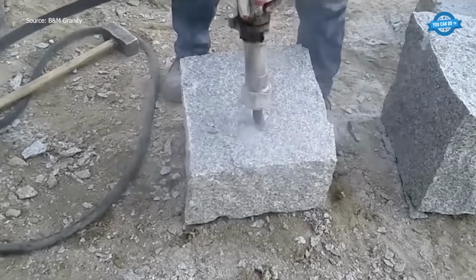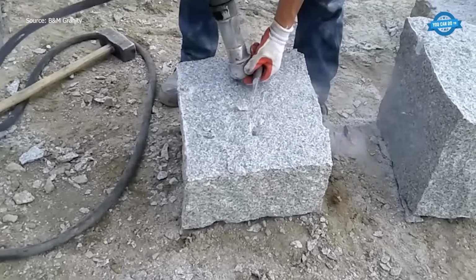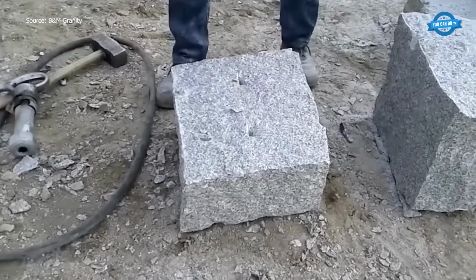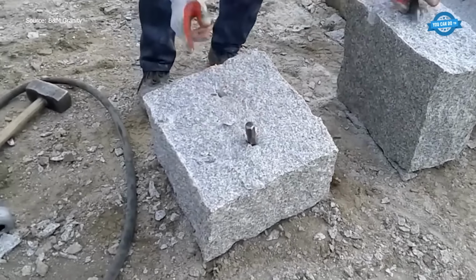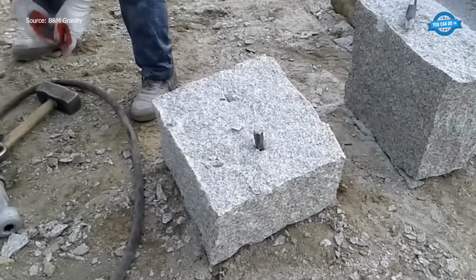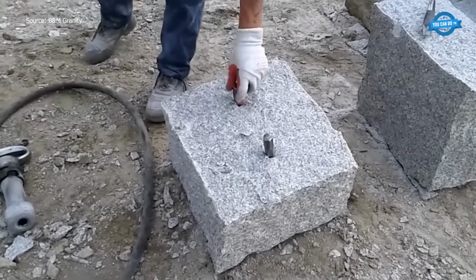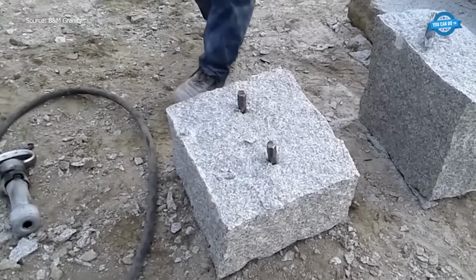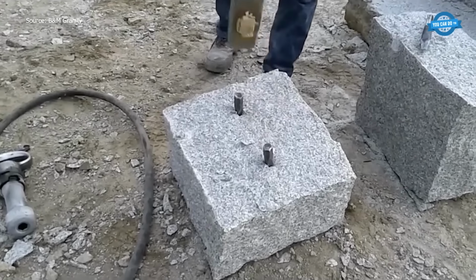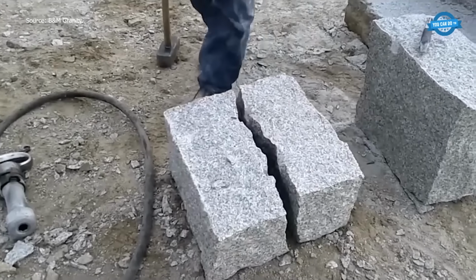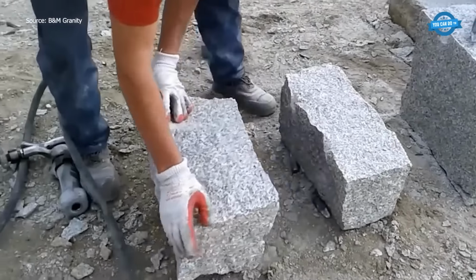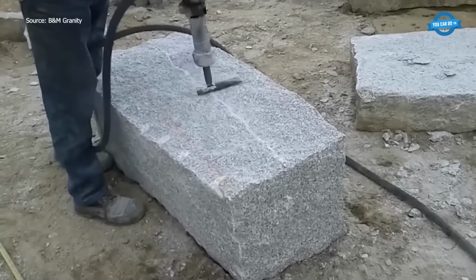Hammer strikes drive the wedges deeper, building internal pressure across the stone. Granite does not flex. Stress accumulates until a clean crack travels through the block. That sharp fracture still catches you off guard. The oversized mass separates into smaller sections, sized for secondary processing, such as splitting into paving elements or cut stone pieces.